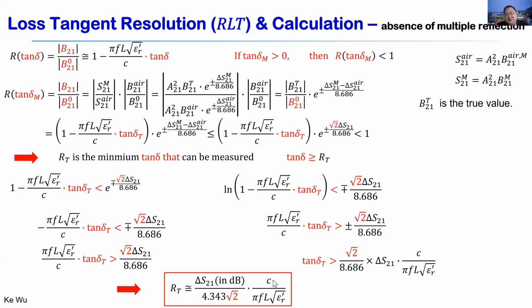Which means that we should be able to develop the test setup which allows us to make the parametric extractions, and the loss tangent value should be larger than these values. Otherwise, the resolution of the loss tangent parametric extraction is not correct enough. So that's why this gives us a very good assurance about the accuracy of the loss tangent.